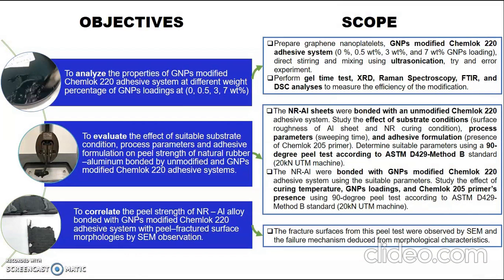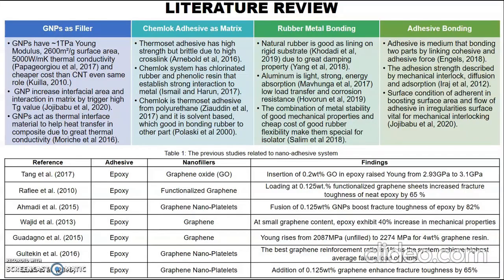The objectives relate to the scope. The first objective is to analyze the properties of modified graphene adhesive system at different weight percentage of GNP loading by XRD, Raman, FTIR, and DSC. Secondly, to evaluate the effect of suitable substrate condition, process parameter, and adhesive formulation by 90-degree peel test according to the ASTM D429 method B. And lastly, to correlate the peel strength of an NR-Al alloy bonded with a GNP modified Chemlok adhesive system with peel fracture surface morphology by SEM observation.